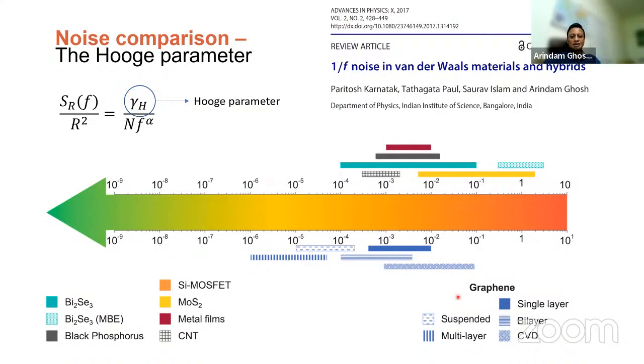And as we looked at different devices, started cleaning them up, started getting a better environment, we have now been able to, this is Saloni's noise level of graphene, single layer graphene noise in 2020 has come down by approximately 3.5 orders of magnitude from 10 to the power minus 1, minus 2, to the level where one of the lowest noise semiconducting devices can now be made from single layer graphene, which we are very excited by, because now we can use them in optoelectronic detection, you can use them as bolometers and so on and so forth, and various device applications where we should be able to get proper response.